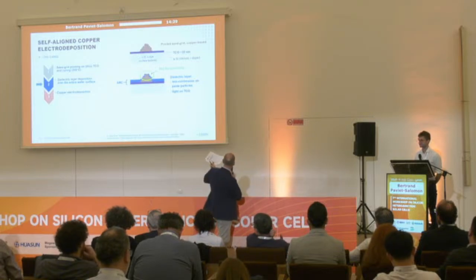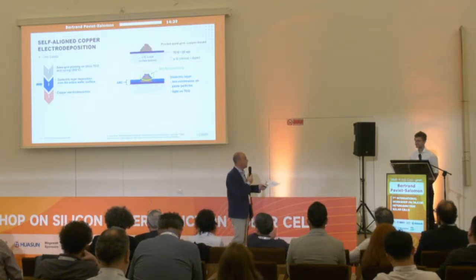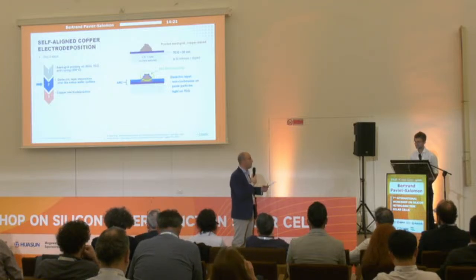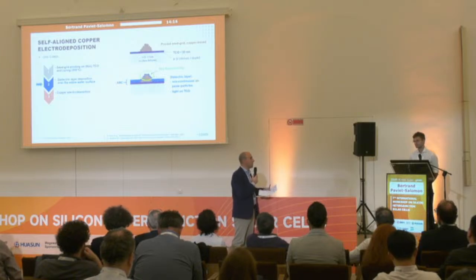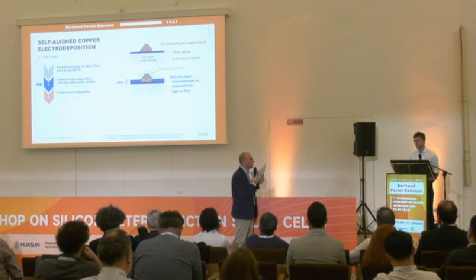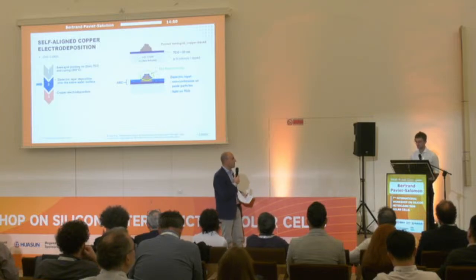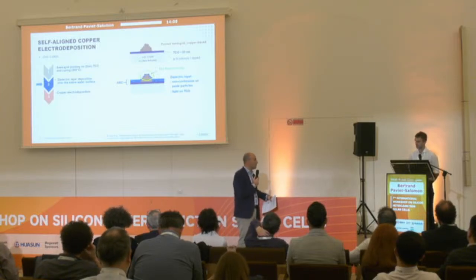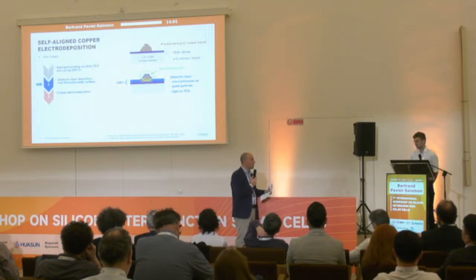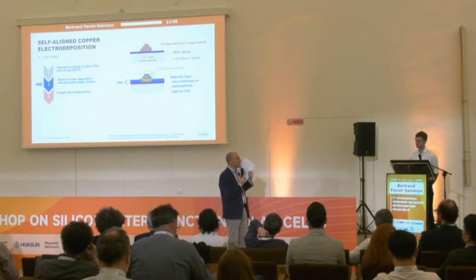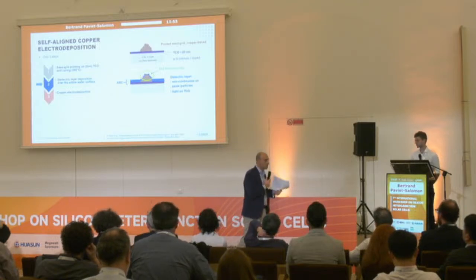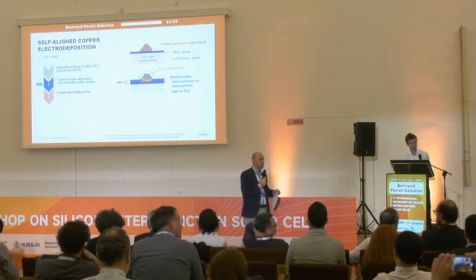My question was, if you have to use PECVD, is it a process that I can imagine can introduce some contamination in your reactor? So you have to clean the reactor, or would you advise at industrial scale to have a reactor per se for this? Yeah, rather the second option. We rather imagine to have a PECVD or an ALD tool at the back end side of the process, because of course you don't want to use the same tool in which you are depositing your intrinsic layer and so on. But then the CapEx will change. But it's taken into account. Thank you.